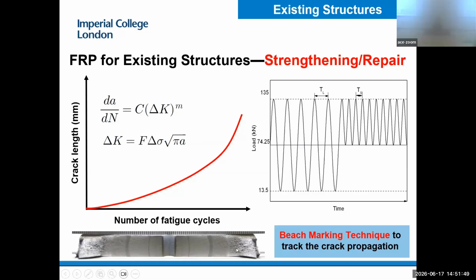So this is the fracture surface after fatigue testing. You can see we created a lot of striations on the surface. By measuring these striations, you can plot this crack propagation curve.